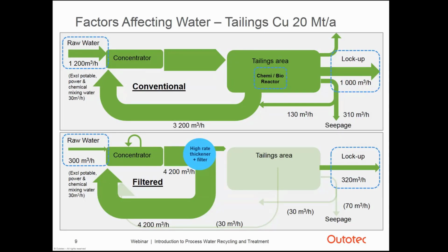If we then look at the filtered tailings on the bottom of the picture, you can see that the raw water needed is much lower, only 300 cubic meters per hour. So obviously we are saving water when using this kind of tailings management. In this approach, we are using high rate thickener and filter approach, so effectively dry stack tailings. We are recovering more water in the dewatering step instead of just having the tailings area and the losses. The lock-up water is much lower. We have only 320 cubic meters per hour. Also, seepage is reduced, so really the losses of water are much lower in terms of water quantity. Another point here, however, is that the quality of water could be worsened and accumulation of impurities can take place.